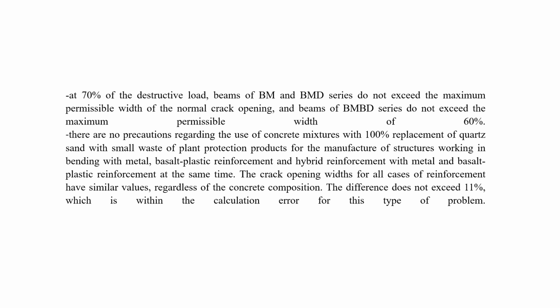There are no precautions regarding the use of concrete mixtures with 100% replacement of quartz sand with small waste of plant protection products for the structures working in bending with metal, basalt-plastic reinforcement and hybrid reinforcement with metal and basalt-plastic reinforcement at the same time. The crack opening widths for all cases of reinforcement have similar values, regardless of the concrete composition. The difference does not exceed 11%, which is within the calculation error for this